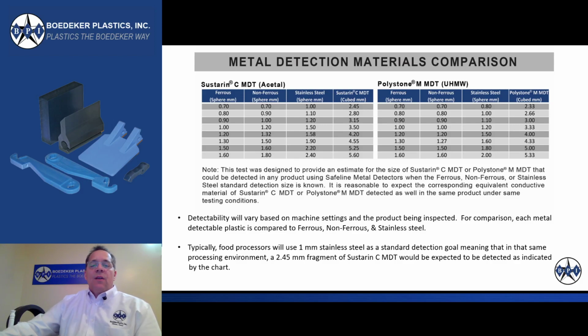And one of the reasons we did that was most manufacturers use a 1 millimeter stainless steel sphere as a good standard. So when we set the system up to that stainless steel standard, you can see that when we ran the ferrous and non-ferrous metals through, those resulted in detectability levels down to 0.7 millimeter. So those materials are actually even more detectable than the stainless steel. And that held true as we went on down to different detector levels. Traditionally, the ferrous and non-ferrous materials were more detectable than the stainless steel.